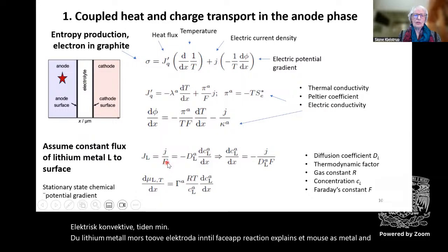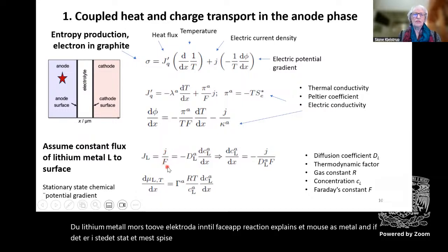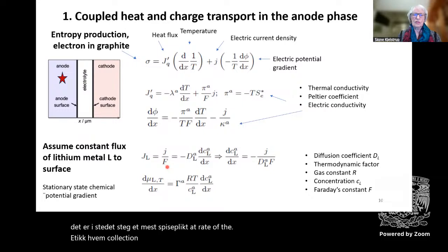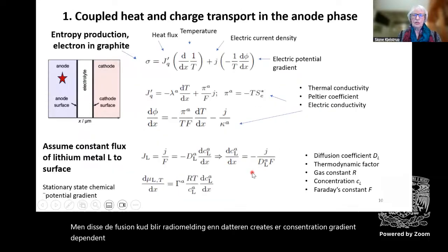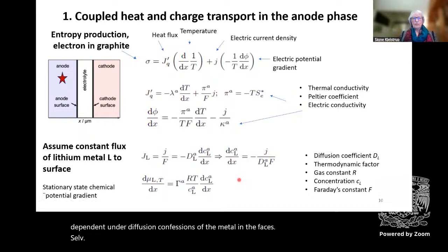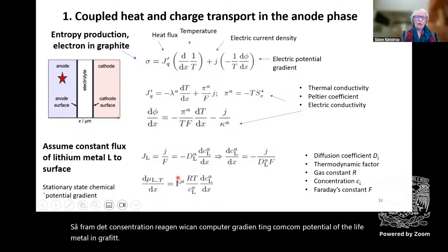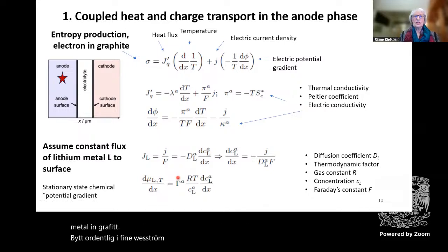And if there is steady state, it must be supplied at the rate of the chemical reaction or the electric current density. And this diffusion could be rate limiting, and that then creates a concentration gradient dependent on the diffusion coefficient of the metal in the phase. So from the concentration gradient, we can compute the gradient in chemical potential of the lithium metal in the graphite. But only if we know the thermodynamic factor, which describes the non-ideality of the component in the phase.